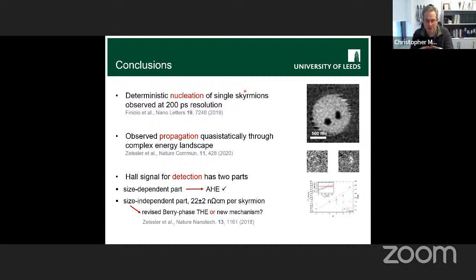We were in a regime where, when the pulse turns off, the thing just stops and fixes at the size that it had reached when that inflation process ended. So that's what we think is happening, and the pinning in the material keeps it at that size.